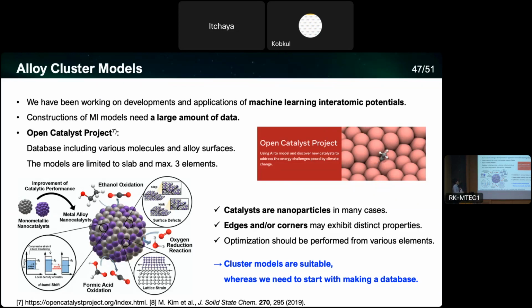So we decided to start to make our own database, partly because the catalysts are considered as nanoparticles in many cases. The slab is actually approximating the nanoparticles in the large limit, but we think there are still differences between the slab and actual nanoparticle calculations. So we decided to use the nanoparticle form. And also nanoparticles have edges and corners, which may have distinct properties compared to the flat surfaces.